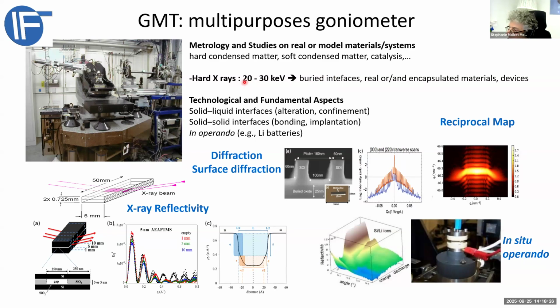So we are using the higher part of energies of the bending magnet source, starting from 20 keV up to 30 keV, for instance, in order to really probe inside the materials. In this case we can cross the top solid or liquid layer in order to probe the interface between the solid and the liquid. And we are also able to cross a solid layer on top of another solid substrate, and then to understand the properties of this interface.